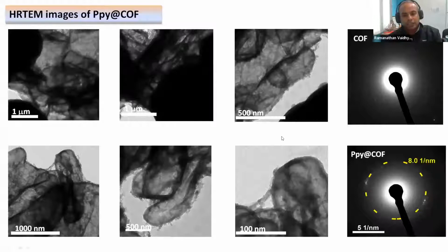And here is the HRTEM image of the polypyrrole loaded COF. You can see that in addition to the COF flakes, there are features which look more fibrous, which are likely to be the polypyrrole. And here is the SAED pattern, selected area diffraction pattern. You can see in the COF case, we do see good crystallinity, but it does decrease to more of a polycrystalline ring pattern when it is treated with the polypyrrole.